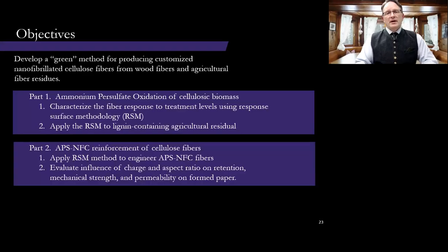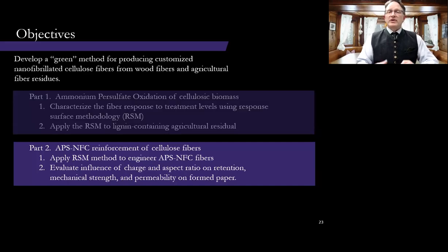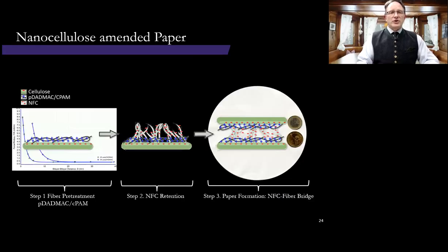So in part 2, I examine the reinforcement of cellulose fibers in a sheet of paper using engineered ammonium persulfate NFC. I apply the response surface method to engineer fibers with a specific aspect ratio and a specific charge. I then evaluate the influence of charge and aspect ratio on the retention of the nanofibrillary cellulose, the mechanical strength, and the permeability of the resulting papers. I'll again first present the methods and then the results. Using the response surface model, we engineered a low charge, high aspect ratio, and a high charge, low aspect ratio NFC amendment for papers.